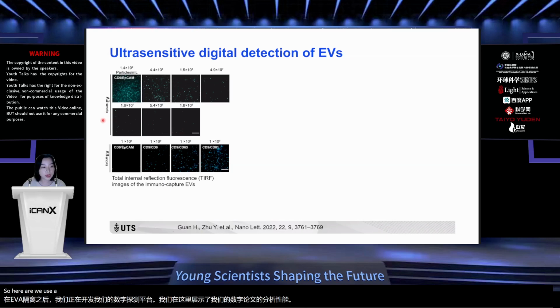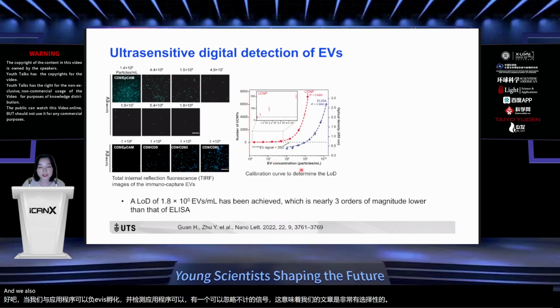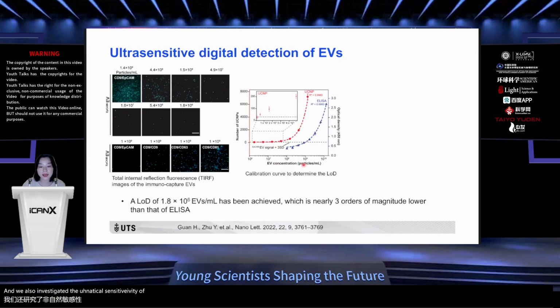Here we use two different types of EV subpopulation, one is EpCAM positive and one is EpCAM negative, to show the analytical selectivity of our assay. When we incubated with the EpCAM positive EVs, there are bright spots showing in the image, and the number of spots increases with increasing incubation concentration. When we incubate with EpCAM negative EVs and detect EpCAM, there are negligible signals, which means our assay is very selective. We also investigated the analytical sensitivity of our assay, and it shows that compared with the standard ELISA, our assay can achieve nearly 3 orders of magnitude lower limit of detection than that of ELISA.